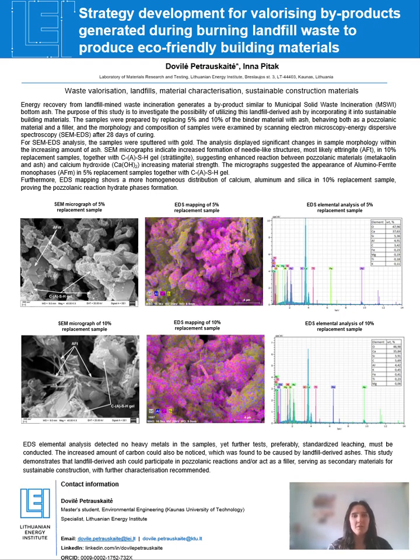So SEM allows us to observe the morphology, the shape and texture of particles, while EDS provides elemental composition maps. And together, these techniques reveal how the ash interacts with the binder and whether new phases form. So magnifications ranged up to 40K, which is sufficient to distinguish crystalline hydrates from amorphous gels.